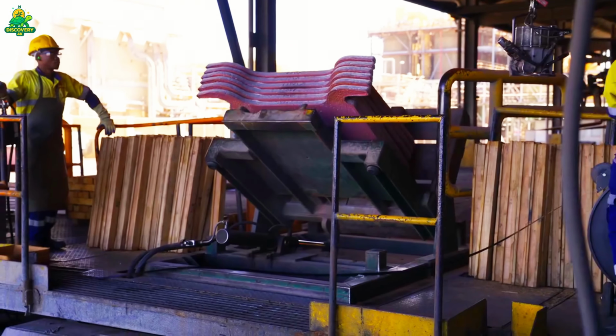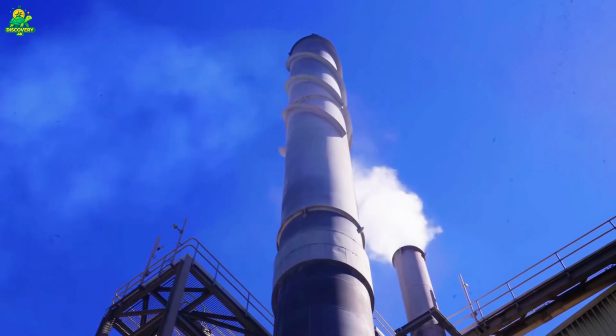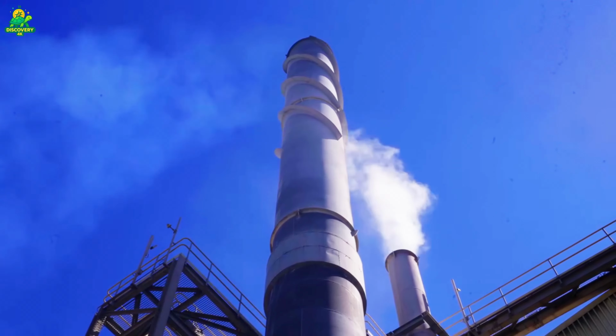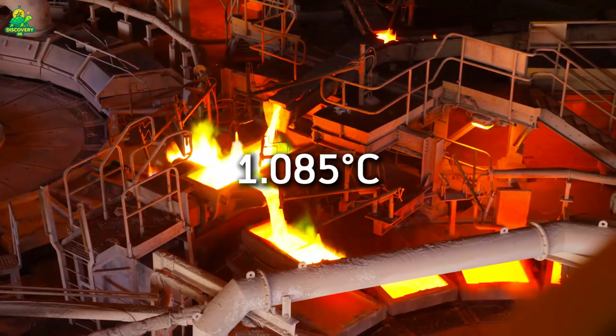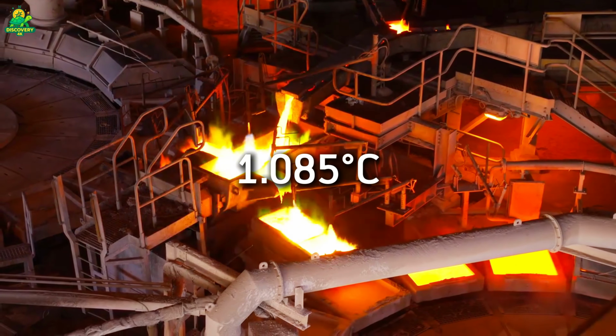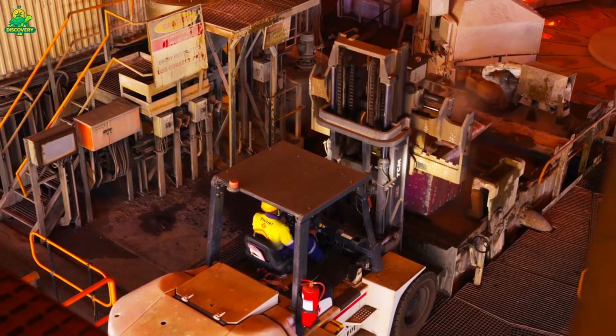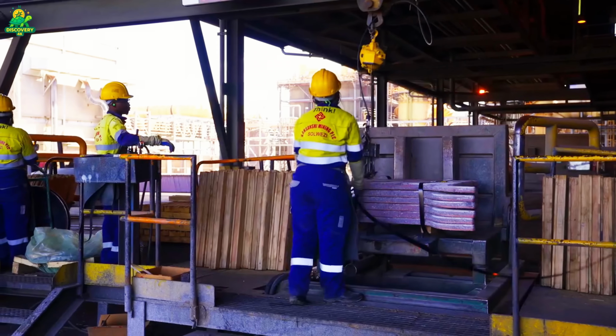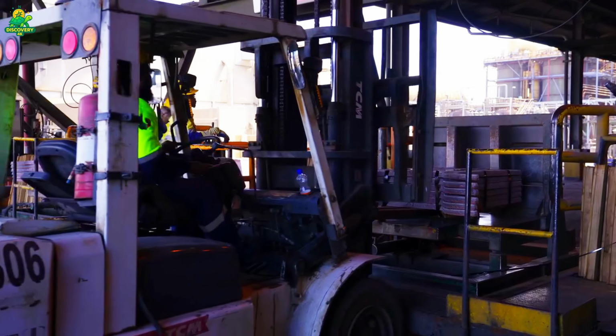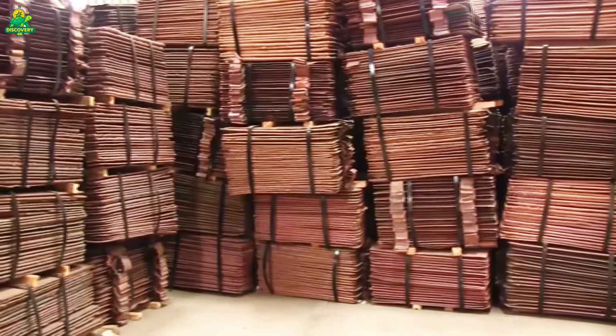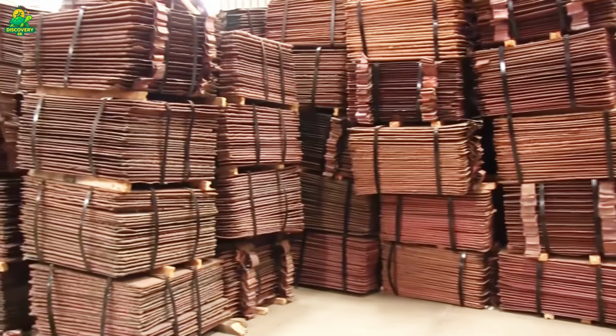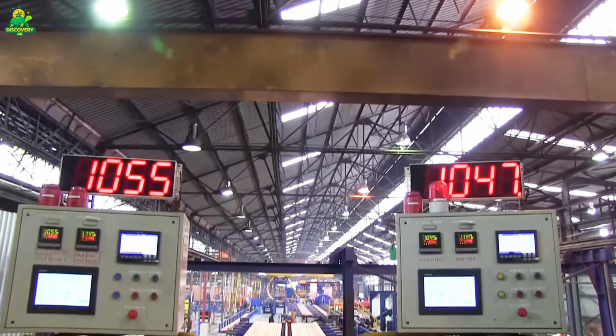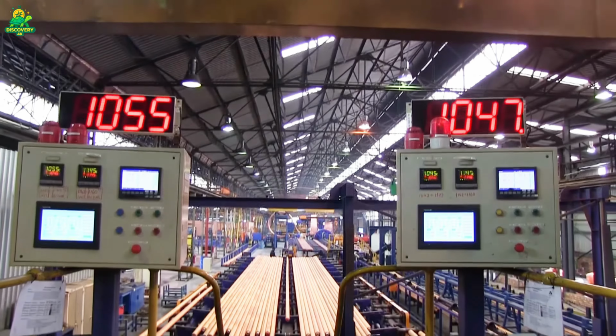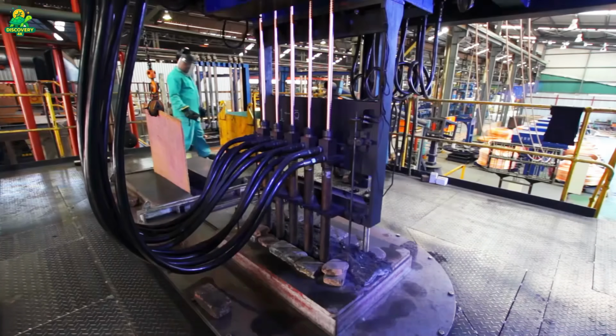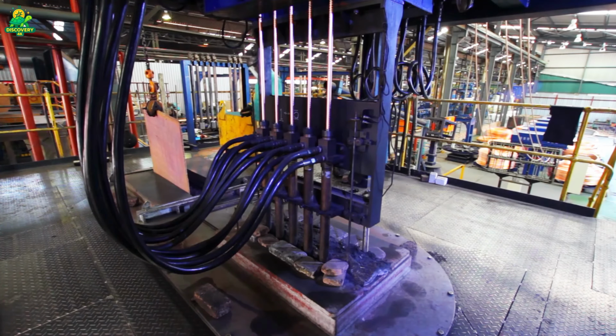Inside the induction furnace, copper cathodes are melted down to a glowing liquid metal. The temperature? 1085 degrees, hot enough to melt steel's soul. Every second, thousands of kilograms of copper flow through channels into continuous casting molds. Here, it cools just enough to solidify into thick cylindrical billets, about 6 inches in diameter and several meters long.